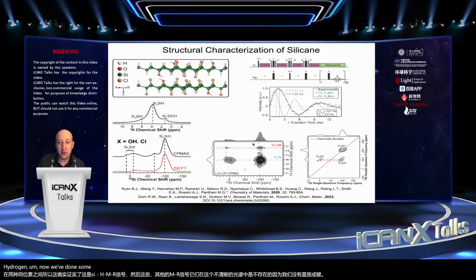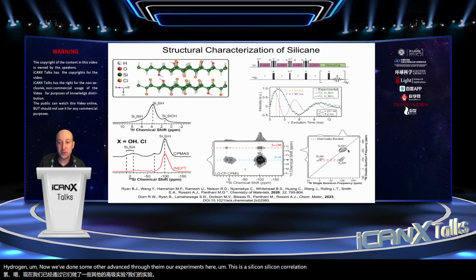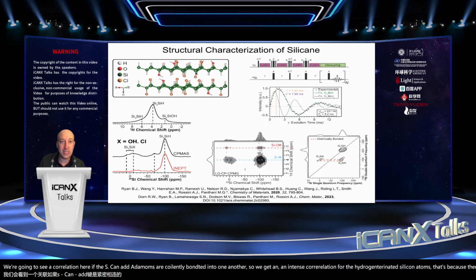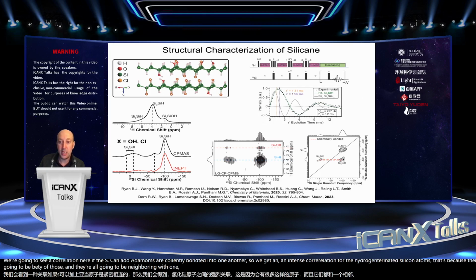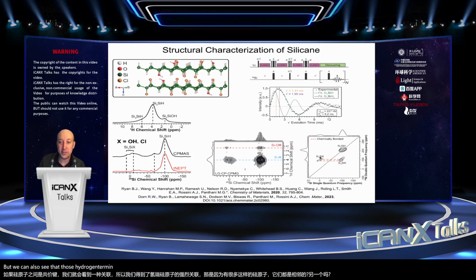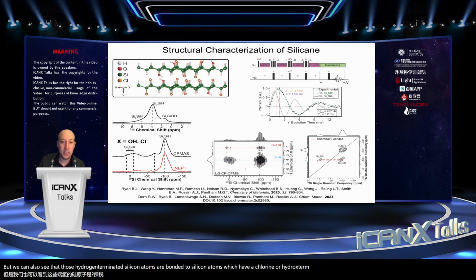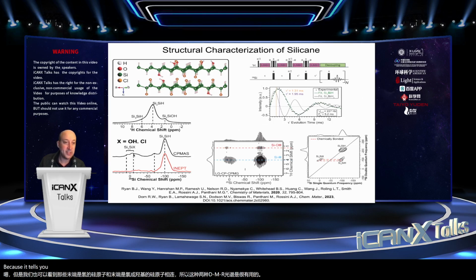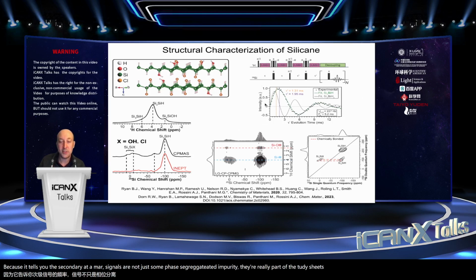Now we've done some other advanced 2D NMR experiments here. This is a silicon-silicon correlation experiment. So we're going to see a correlation here if the silicon atoms are covalently bonded to one another. So we get an intense correlation for the hydrogen-terminated silicon atoms. That's because there's going to be many of those, and they're all going to be neighboring one another. But we can also see that those hydrogen-terminated silicon atoms are bonded to silicon atoms which have a chlorine or hydroxyl termination. So this type of 2D NMR spectrum is really helpful because it tells you these secondary NMR signals are not just some phase-segregated impurity. They're really part of the 2D sheets.